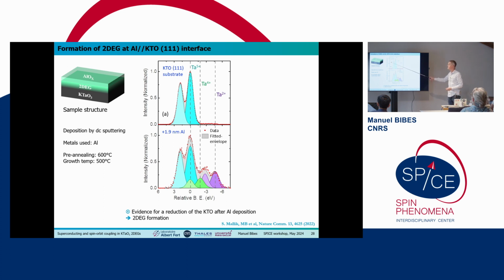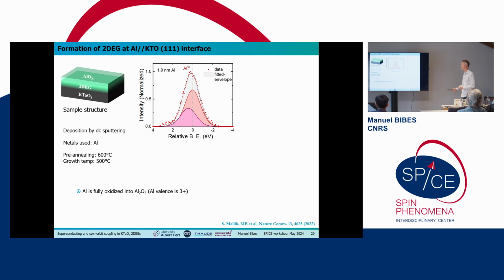Again, we generate the 2DEG by growing aluminum, and these are the tantalum levels before growing the aluminum and after. You can see from these shoulders that we have a reduced KTO, meaning that we have a 2DEG. And this is the aluminum. We can see that it's purely oxidized aluminum 3+, even for 1.9 nanometers. So the aluminum does not contribute at all.